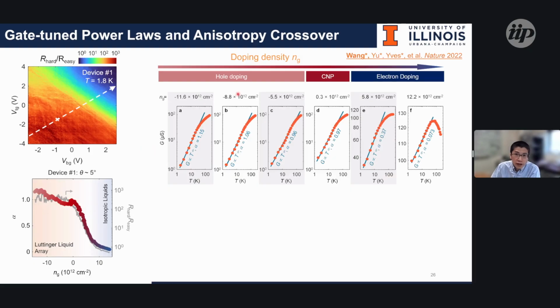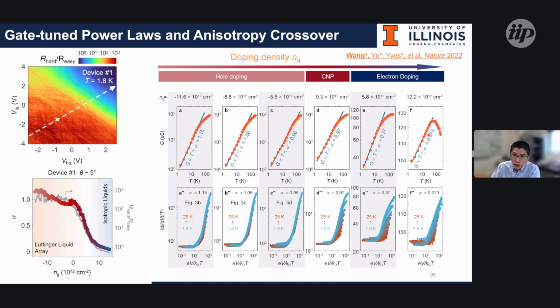Moving further, beyond this well-fitted power law region, there is another region where the resistance has very little change—almost not changing with temperature dependence. This also appears in the fitting at very high doping density, very high electron doping. So we suggest that to see such power law behavior with good scaling, you need to tune the gate across the whole doping region.